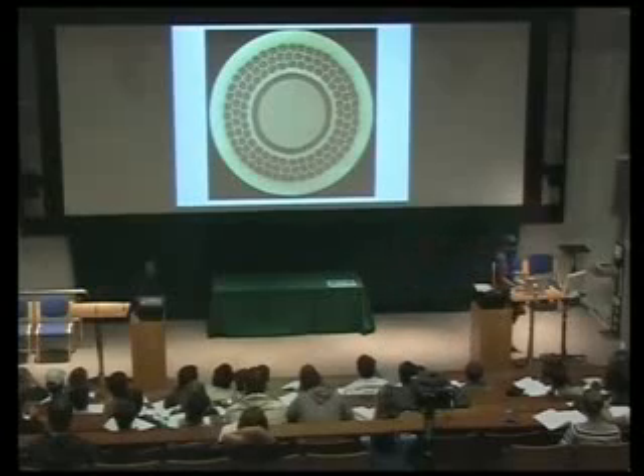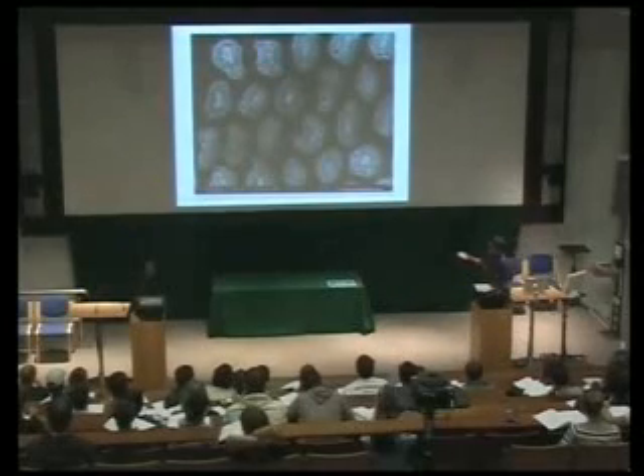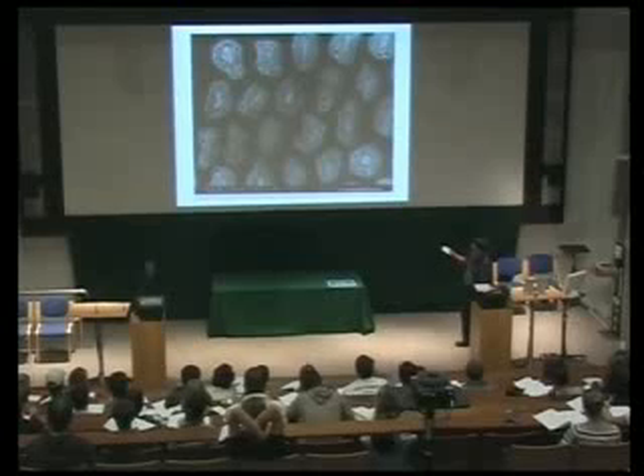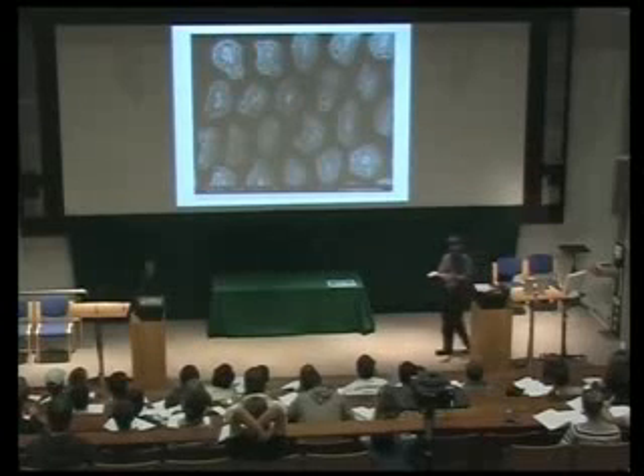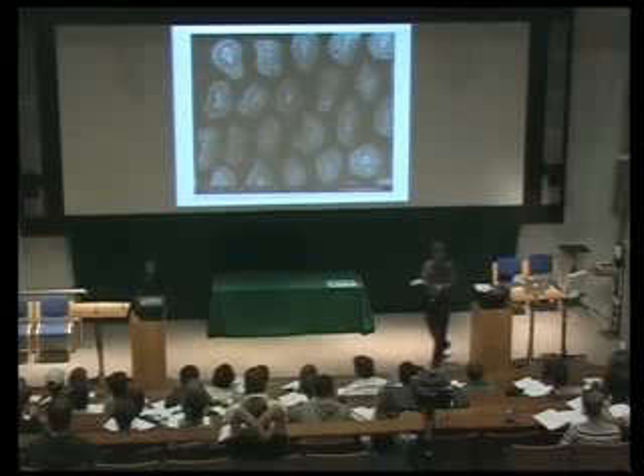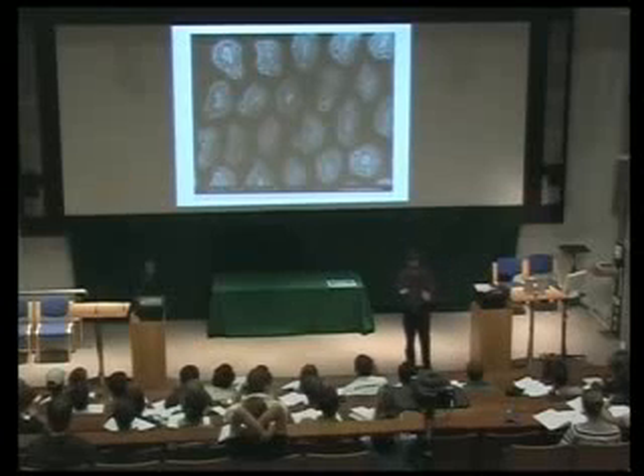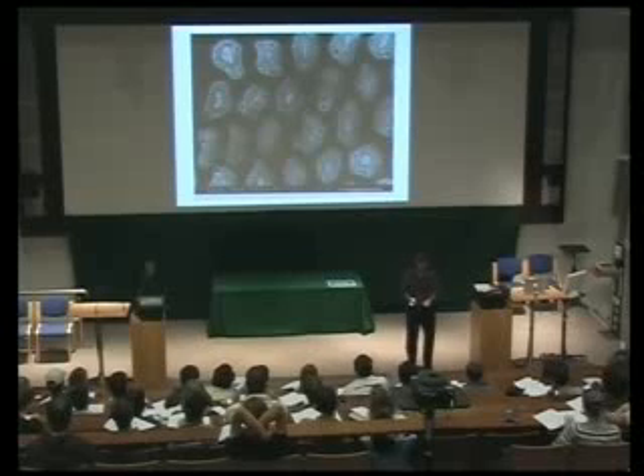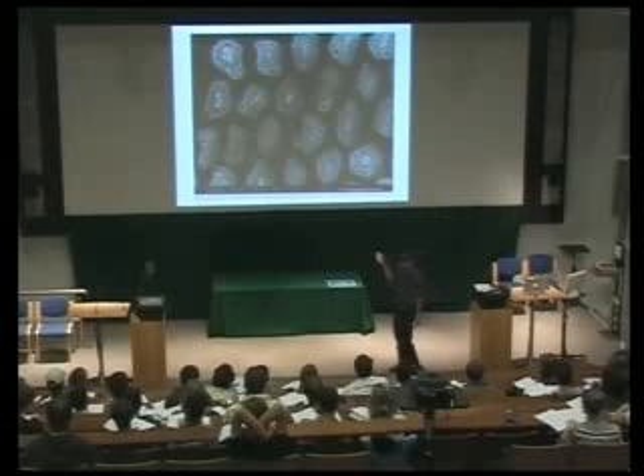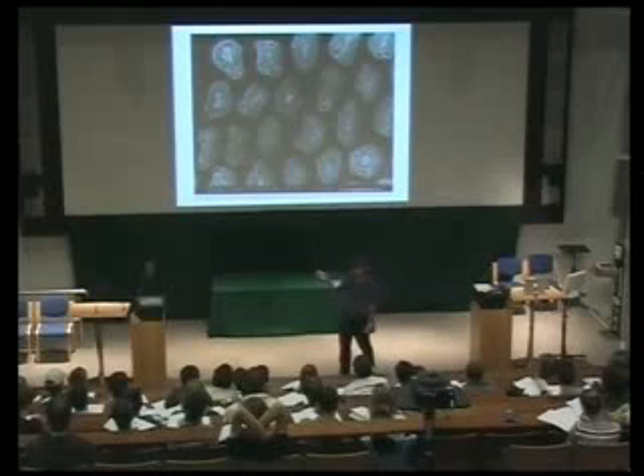What you end up with is porosity. You see all these holes? That's, again, because the diffusion coefficients of niobium and tin are so different that you will get a net flux of vacancies which creates holes. Now, it actually doesn't matter in this application.